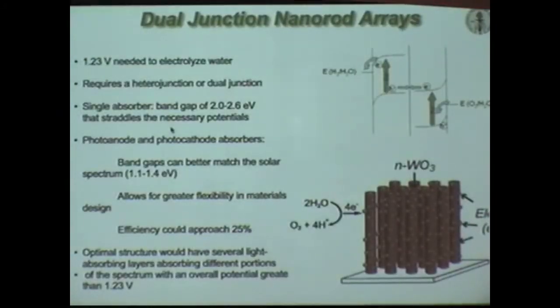The other piece of plastic is going to have the rods that are oxidatively stable, and so we've started working on that part of the problem with tungsten oxide and had some success growing those rods. Silicon's going to be below because it's a known photocathode. Tungsten oxide should be a known photoanode. It gives us 800 millivolts voltage. You need 1.2 to split water. We already have 450 from the silicon.